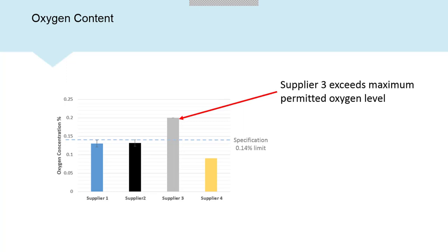Problem is I can't use the 0.2 very many times before it goes out of spec. So when we're specifying AM powder, we generally want to go to a much lower one. Perhaps when you're buying in titanium 6-4, you might want to go to the ELI grade, the extra low interstitial. That gives you quite a good margin in which to pick up oxygen in the process.